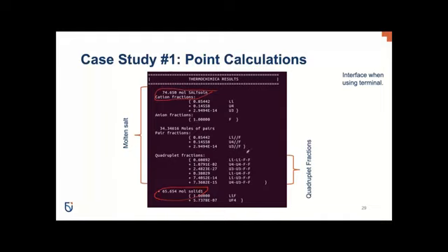So in this case here, remember I was giving a very high-level overview of the modified quasi-chemical model where you're dealing with quadruplets. In this case, the primary sublattice has lithium, U3 and U4 on the primary lattice, and then only fluorine on the second. So here you can see that you have all of those combinations of quadruplets shown here. And then these, again, are the quadruplet fractions. Then we have the solid solution at the bottom, and this appears to be represented by a regular solution model, which is predominantly lithium fluoride with a practically insignificant amount of uranium tetrafluoride dissolved in it.